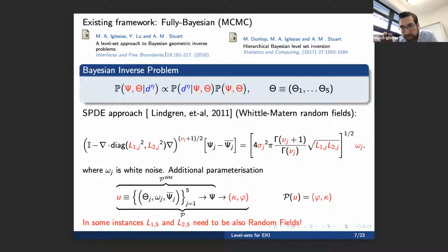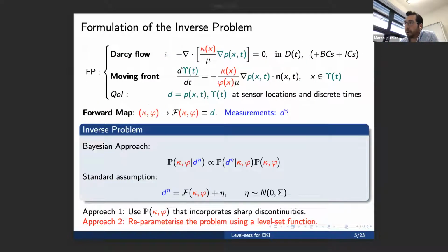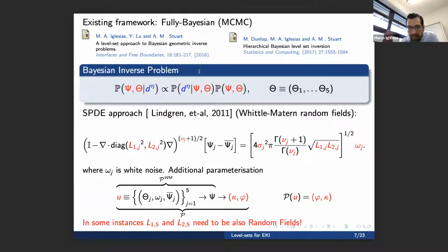And I have to emphasize that this Darcy flow problem, this moving front problem, is a few orders of magnitude more complicated than the standard Darcy flow that you will normally see in UQ examples. This is more equivalent to a 2-phase flow, where you are replacing air. And that's, again, much more challenging, and it requires much more computational resources to solve than a simple Darcy flow because of the moving front. And the reason why we adopt this setting of moving front is because in the industry for composites, there is software that allows you to solve for this within the application for the resin transfer molding that I described. So I just wanted to make this comment.